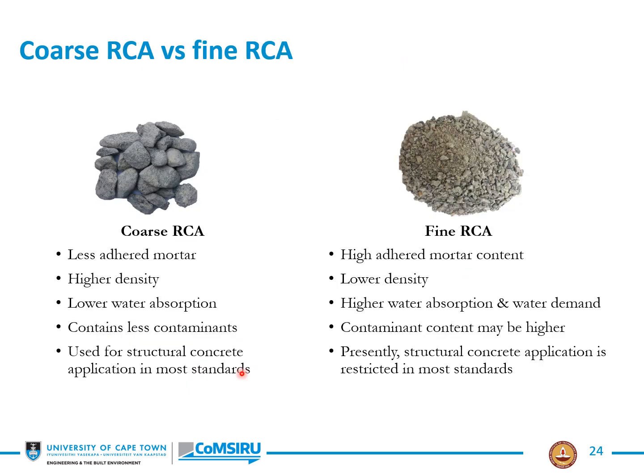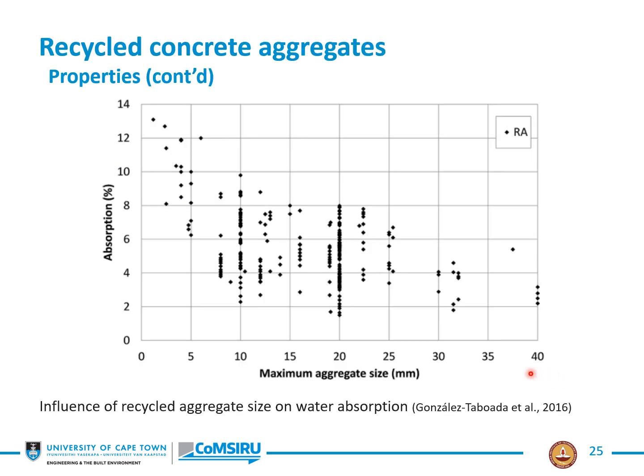And here again, there's a comparison of coarse RCA with fine RCA. In this case, less adhered mortar, higher density, lower water absorption, contains less contaminants, used for structural concrete applications in most standards. Whereas here we have the higher adhered mortar content, lower density, higher water absorption, contaminant content may be higher, and presently this material is quite restricted in most standards. And here is an illustration of some of those points.